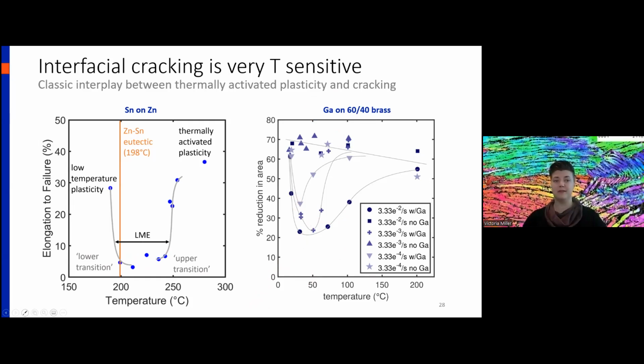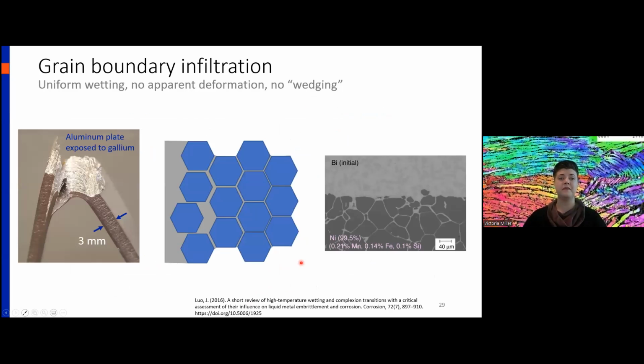The second proposed mechanism is grain boundary infiltration. So this would be wetting of the grain boundaries. What this looks like is you get uniform wetting along the boundaries. You don't get any apparent deformation within the grains, and you don't get any wedging. So you don't get any variable thickness of the grain boundaries in any meaningful way.